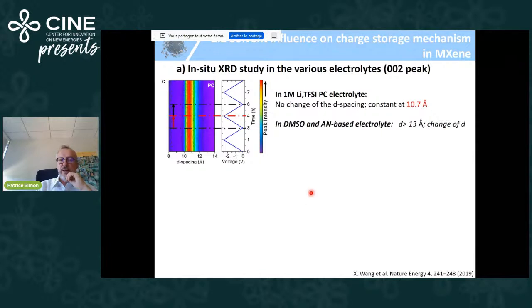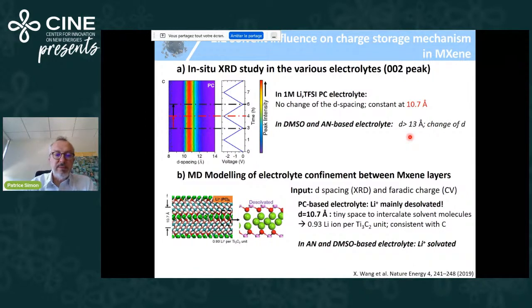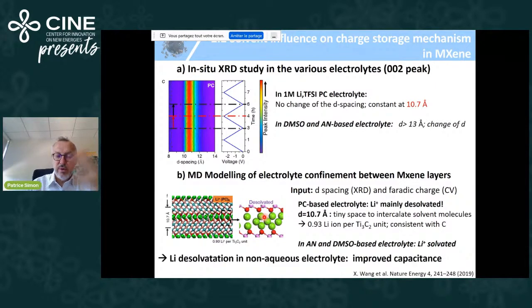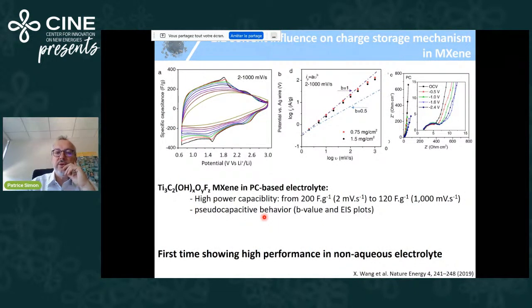And then we tried to understand what was happening in these electrolytes. You see here the change of the 002 peak during polarization by XRD. So we tracked the position of the 002 peak by XRD, and what you see is that during insertion and deinsertion, there is no change in the 002 peak position. So it means that there is no change in the spacing of the MXene when you put lithium in and out. Differently, in the other solvents, yes, there was a change. And more interesting is that by molecular dynamics modeling, we saw that the only way to get this high capacitance and this spacing was to have lithium mainly desolvated between the layers. So the message is that when you have lithium which is mainly desolvated between the layers of MXene, you improve the capacitance, you reach high capacitance and fast redox processes. So this desolvation process seems to be quite universal, I would say.